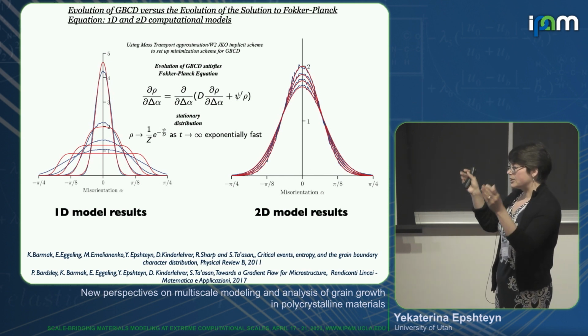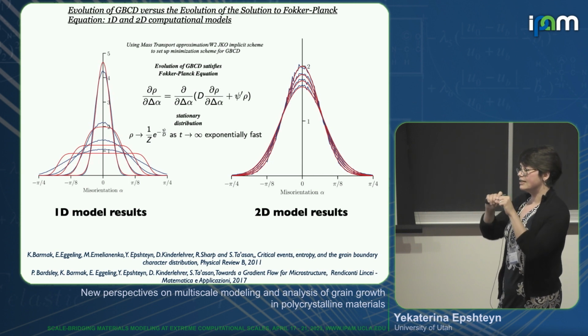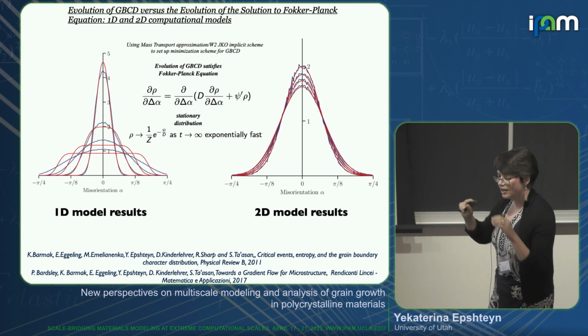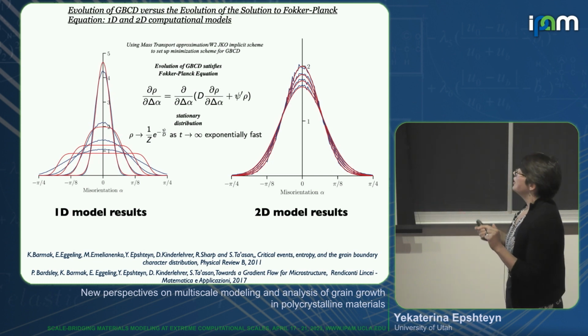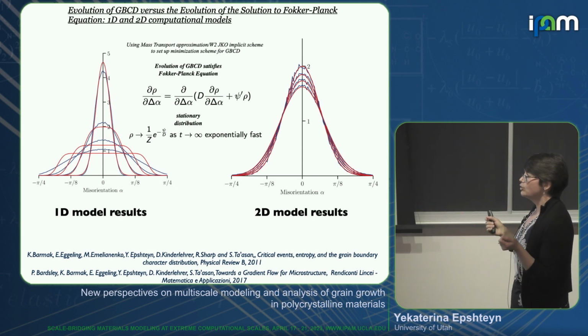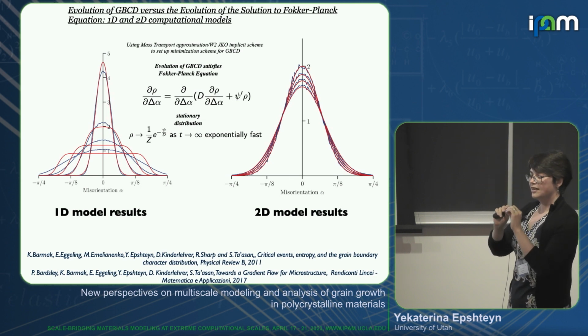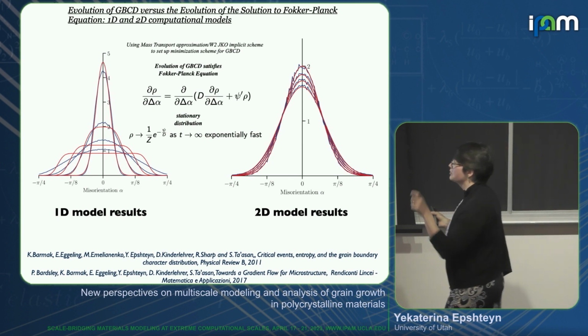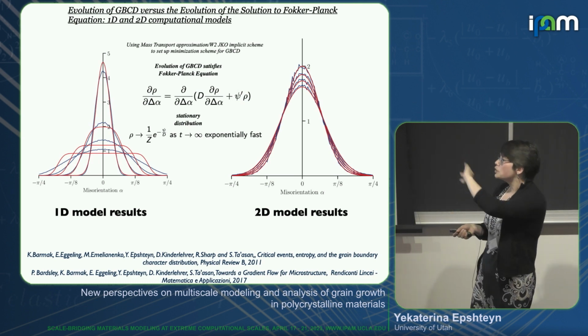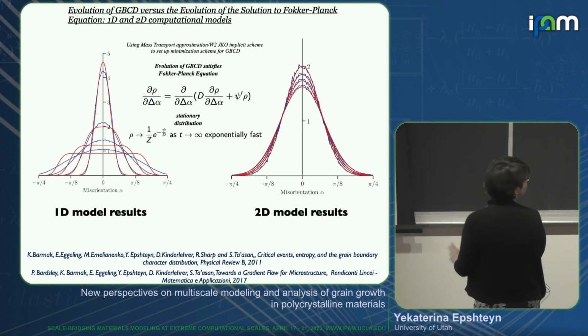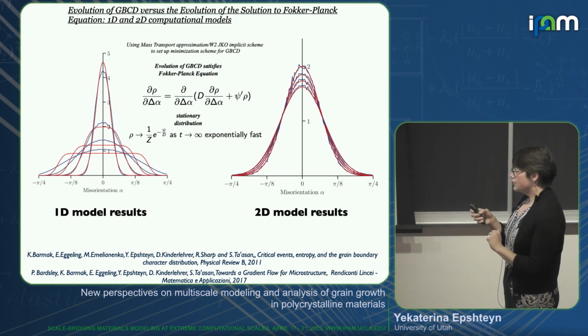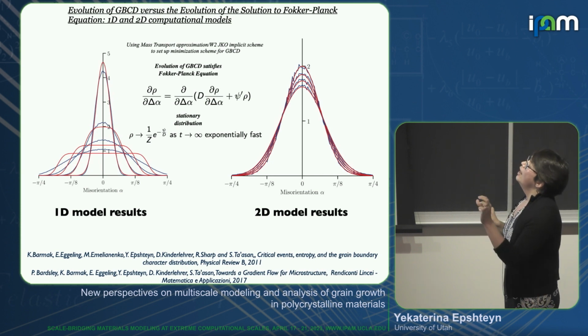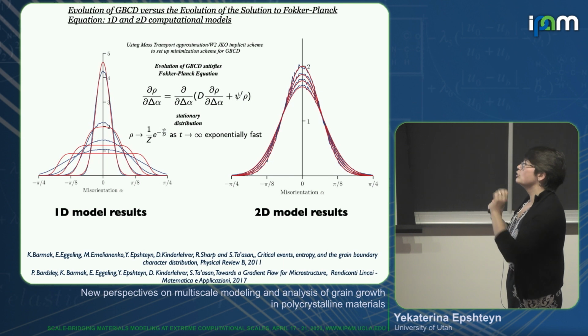Let us model the grain growth using some kind of evolution of triple junctions and interactions with misorientations. And what we did, but we oversimplified at that time, we basically stretched the entire cellular network on a 1D line. And we reduced the entire 2D cellular network to a 1D coarsening network where grain boundary was represented by an interval. Not going to go into details of that model due to lack of time, but what we were able to show using a reduced 1D model that didn't really model triple junctions, because the triple junctions became the endpoints of 1D intervals.